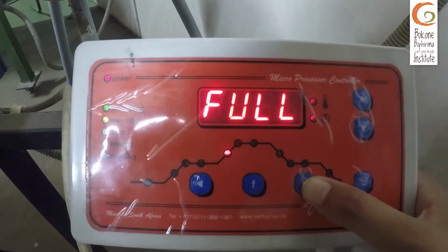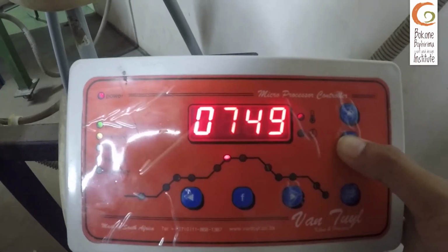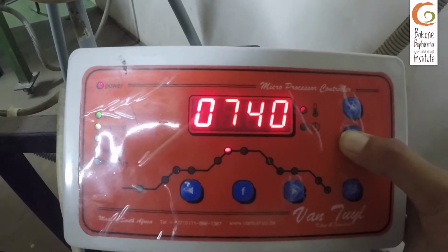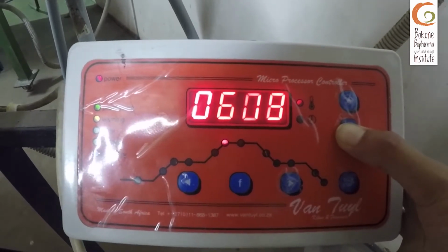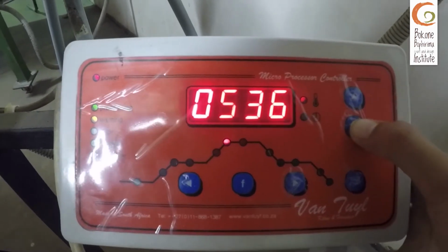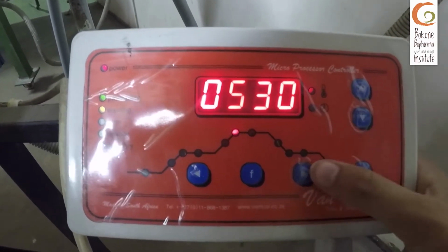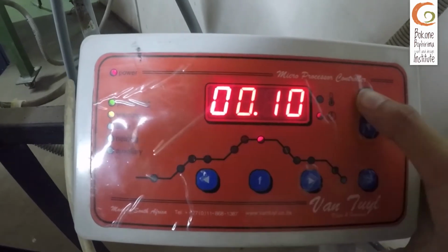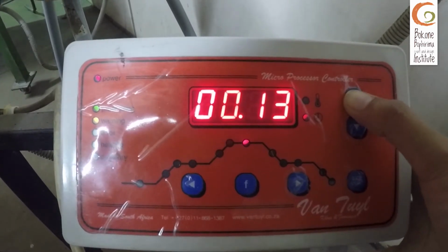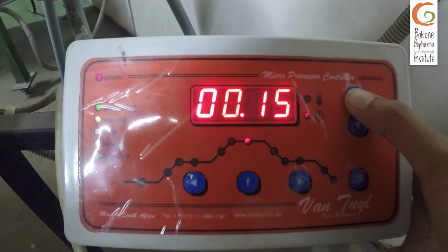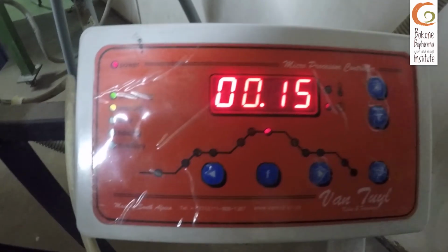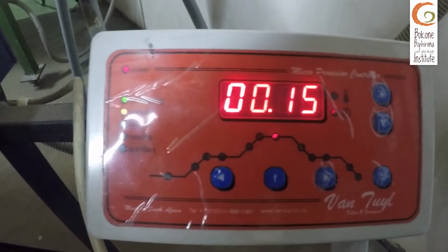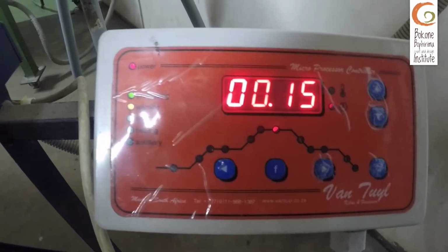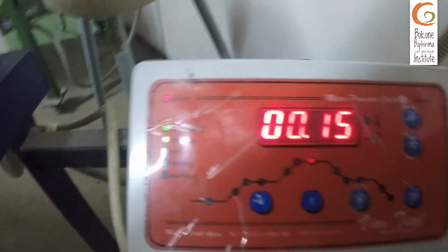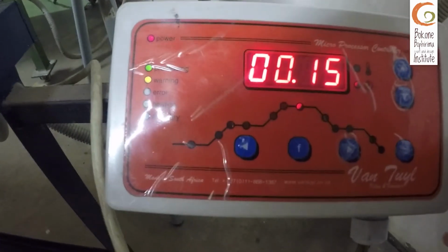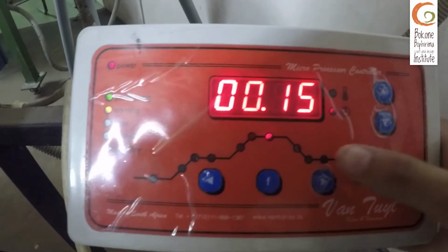We let the glass ramp up fully all the way to our top temperature, which is 530 degrees. We let our paint soak at that temperature for 15 minutes. This is just to ensure that the glass and the paint get consistent heating all around, and that there's no tension between the glass.